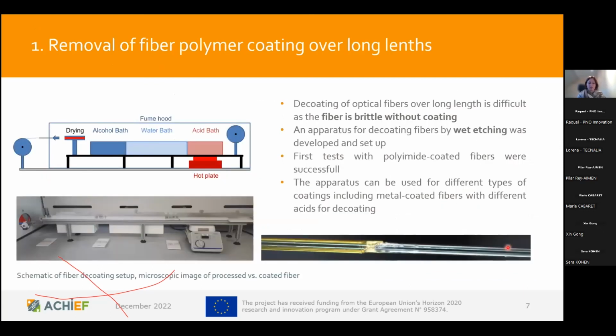So, walking you through the different single results that we got. First, the decoating of the fibers. Here we set up an array of etching baths to remove the polymer coating of commercial fibers. And the difficulty here is that the bare glass fiber is quite brittle without the coating. So we had to find a way to make it in a continuous but also careful manner. And you see here that there is the removed coating from the fiber. Depending on the type of coating, you can use different etch baths to make sure that you clean the fiber properly.